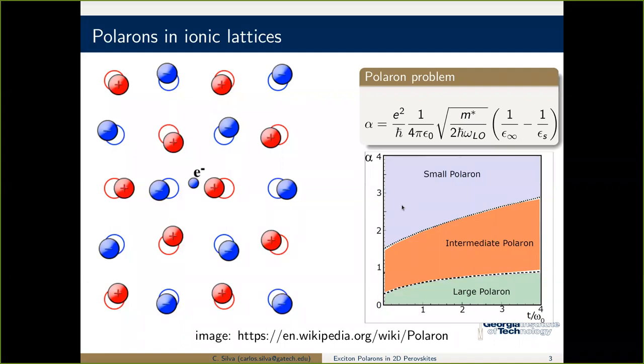So what is a polaron? A polaron is a charge that is dressed by the lattice, that can range from very local interactions to very long range interactions. Over long range, the distortion is perceived through the phonons of the system, the normal modes that couple to that electron. If the coupling is over a very small range, you tend to localize the interaction and you're in the small polaron regime, so that you can categorize things in a phase diagram like this.